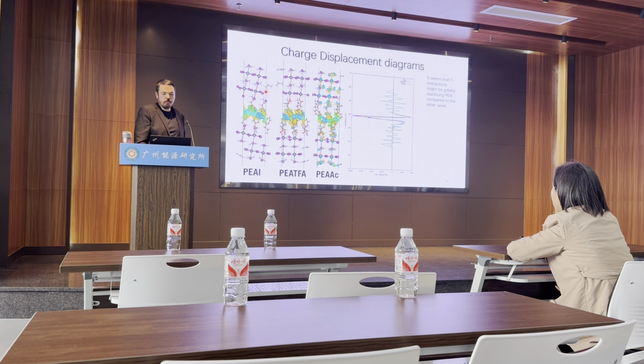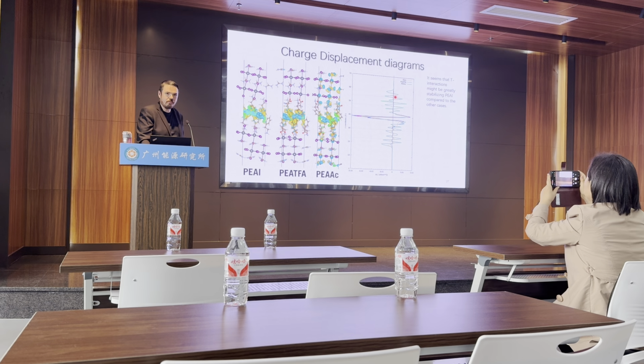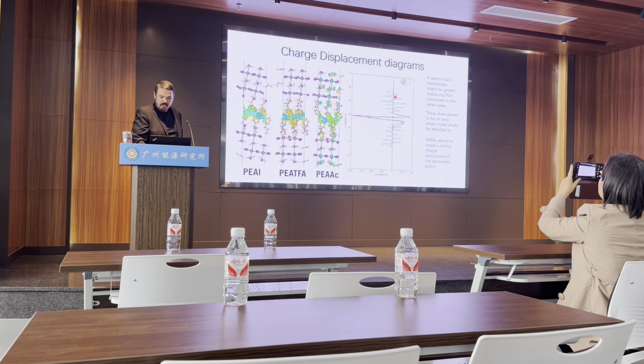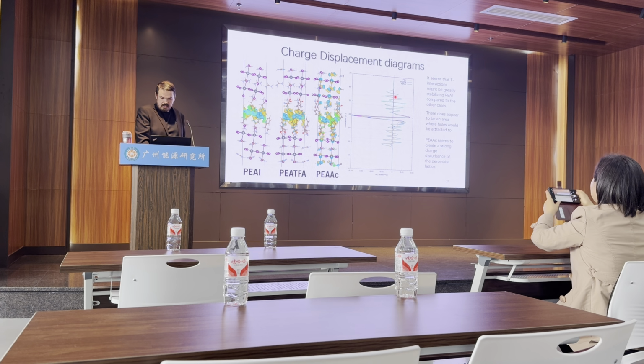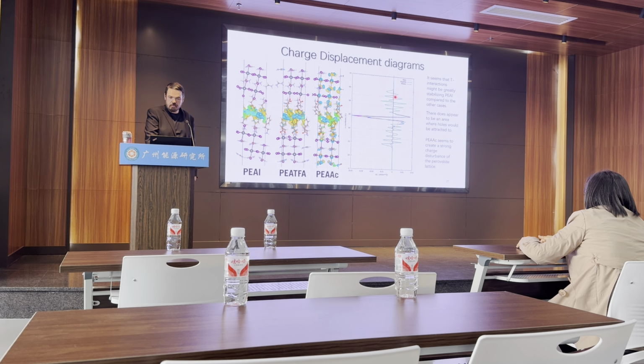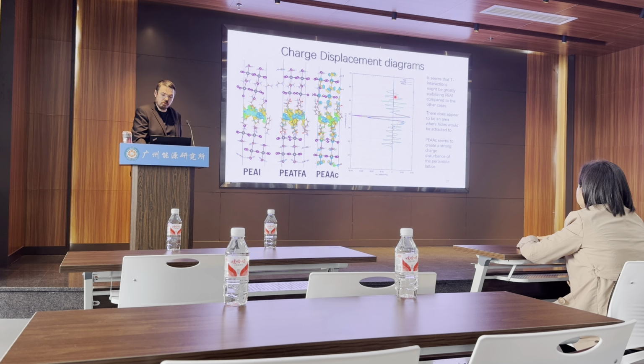And why is PEAI more stable? Well, when you look at it, it's slightly more crooked, so it shifts a little bit. And by shifting a little bit, it optimizes the pi-pi interactions. And apparently, TFA and acetate don't have as much freedom to shift, so they stay more linear, and thus are not as stable. And the acetic-based one is the most linear. You can see that when it's very linear, it actually starts to displace charge throughout the perovskite. This is a very interesting result, to be honest, and also warrants some more investigation, so lots of things to think about here. So acetic acid creates a strong charge disturbance in the perovskite lattice, and the other one's still interesting.